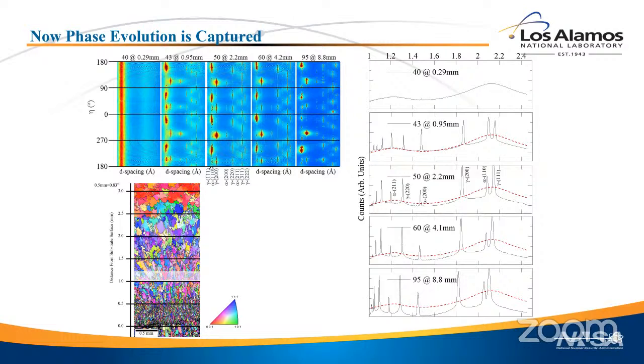And you can also see those two peaks that I pointed out are almost the same intensity at the start. As you move down, and this is on a log scale, so it's a little bit muted, you see that the peak on the right here becomes stronger than the peak on the left. Well, this is the austenite, that's the ferrite. So what you're seeing is the phase transformation from ferrite to austenite as the relative amount of those two peaks change.